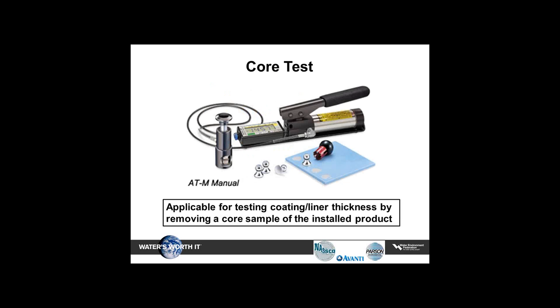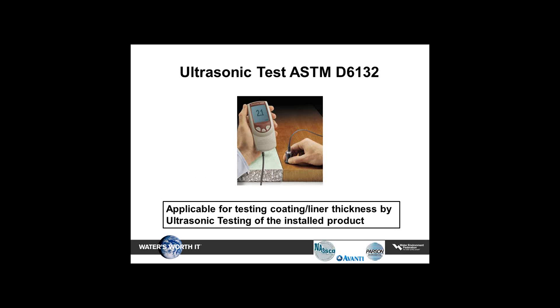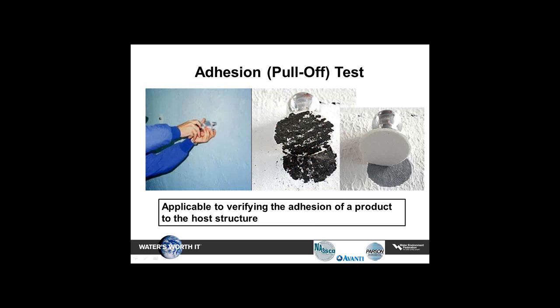The core testing. Core testing is a way of actually removing a small core out of the material that was applied to measure the final thickness. This is a measurable specified requirement in most contracts, and so it can be measured using a core test. Ultrasonic test is a non-destructive way of testing the thickness of coating. Many contractors use this as opposed to actually cutting a sample out and then having to repair that defect. This is applicable, again, for testing the coating and liner thickness by ultrasonic testing of the installed product. Very, very common way of testing the thickness.